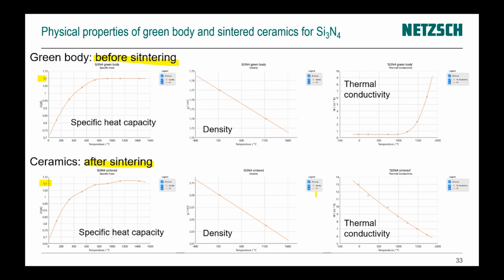And finally, the density of our ceramic product is much higher than the density of the original green body. For example, for silicon nitride, the original green body has a density of about 1.7, and after sintering it is more than 3. So it is almost a factor of 2 change in density during our process.